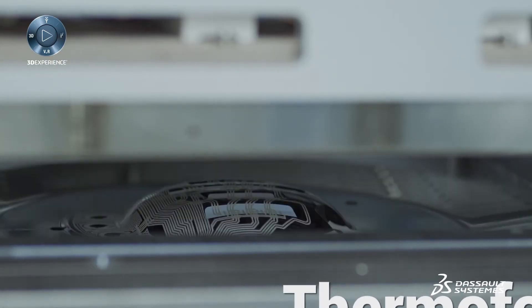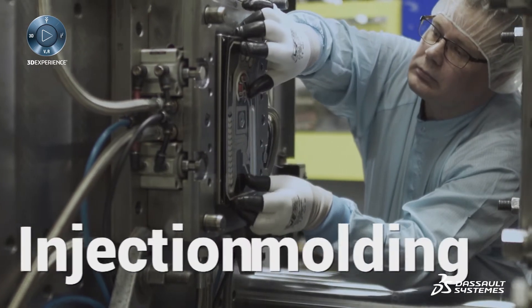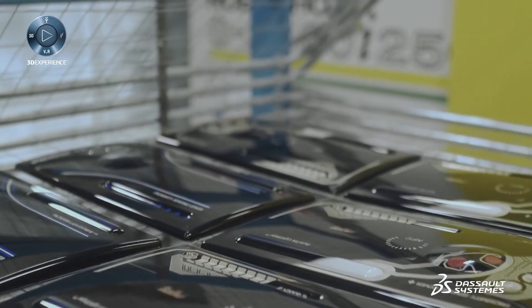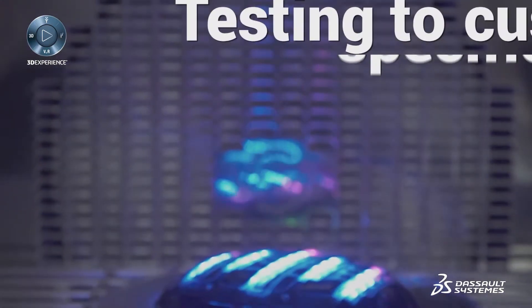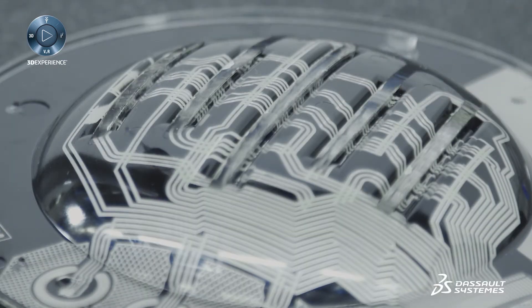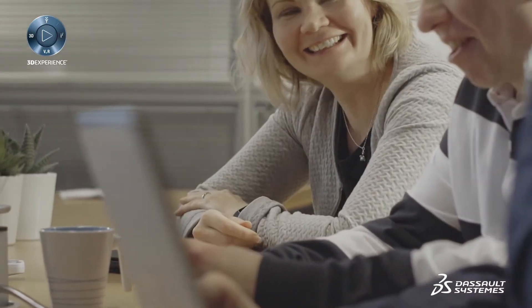Printing decoration and electronics is the first manufacturing step. Surface materials, decoration, and electronic functions are easily changed for cosmetic and functional product updates. Electronic components are placed on two-dimensional film using standard high-speed equipment that enables rapid mass production scaling. Sophisticated cleanroom operations enable consistent product quality. In thermoforming, the part takes on its three-dimensional shape. Formed IML films are injection molded, encapsulating electronics in plastics and creating a single part that often replaces multi-part traditional electronics. Validated IMSE designs are ready for mass production.